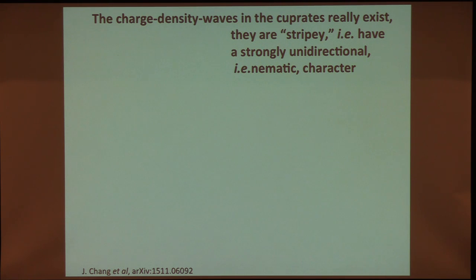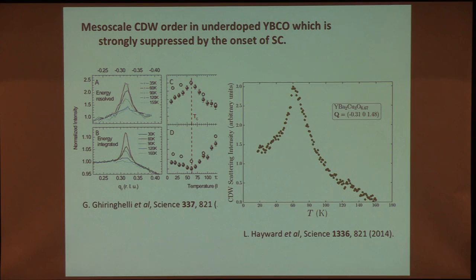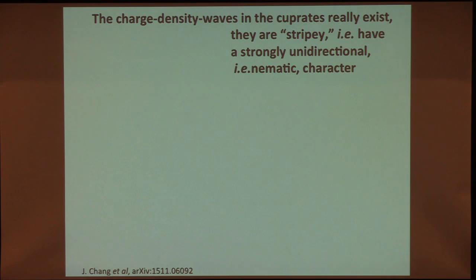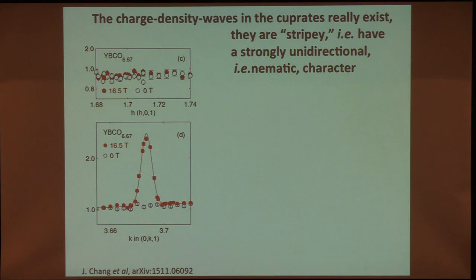Within the last year, it's been discovered that superconductivity and charge density wave order compete. So if you want to see what this charge density wave is really made of, you would like to suppress the superconductivity. To do that, one goes to high magnetic fields, in order to see what the fully ordered charge density wave ground state looks like. And here's what it looks like.